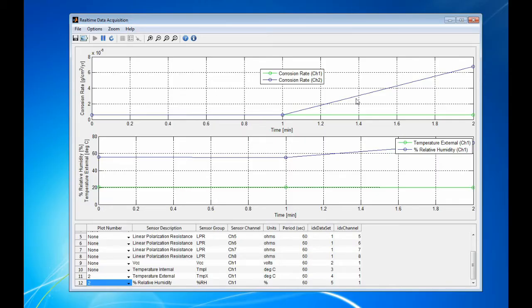So as we can see on the screen, the electrolyte has penetrated the defective coating. Channel number 1, which is the sensor under the intact coating, corrosion rate stays relatively 0, and it's greatly increased under sensor number 2. The sensors have a very quick response time, and they're very sensitive. And as you can see, in the vicinity of the sensor, because we've added moisture, the relative humidity has increased. And although it's harder to see, the temperature has actually decreased slightly because of evaporative effects in the vicinity of the sensor.